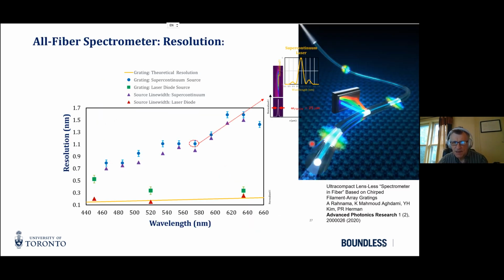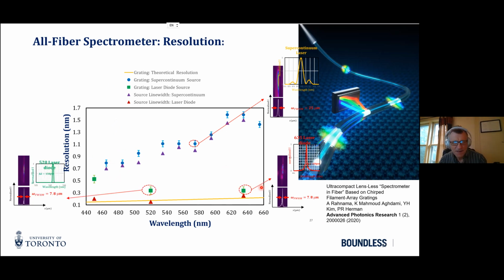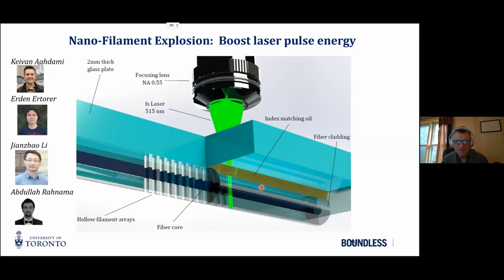So there's a cartoon of the device here. This is a recent publication on the device. And here we're measuring with different sources, line widths, and we're getting about 0.3 nanometer resolution from a device that's about 1 millimeter in length. So it's really quite, I think, an interesting way of making compact optical devices.